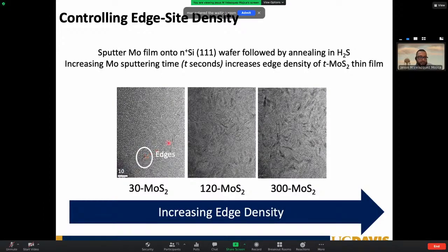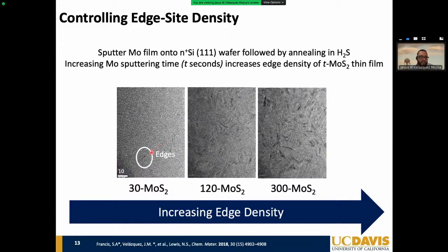And as you increase the thickness of the magnetron sputtered molybdenum film on the degenerately doped silicon, followed by thermal conversion using H2S, you can control the population of those edges. So these numbers mean that we sputtered 30 seconds of molybdenum, 120, and subsequently 300 seconds of molybdenum, followed by sulfurization at high temperatures, and we can then control the edge population.